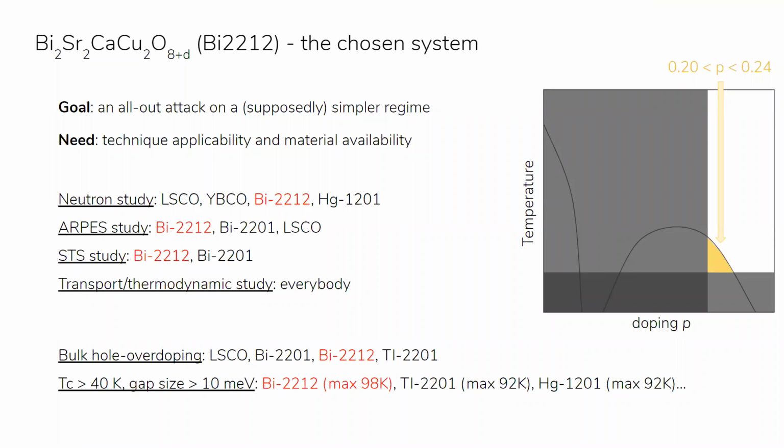To put it short, when we talk about homogeneity, it always has a length scale attached to it. STM has already observed nanometer scale inhomogeneous electronic density of states locally in overdoped systems. In particular, this is not just specific to overdoped cuprates. It's persistent for all dopings. Then we start to talk about chemical inhomogeneity. This inhomogeneity may be characterized by either thermodynamic or magnetic measurements, and those types of inhomogeneity are small. So in that case, we have to treat it in two different ways. If we talk about nanoscale electronic structure inhomogeneity, it's always there. But if we talk about whether the bulk TC transition is sharp or not, then it can always be made very sharp.